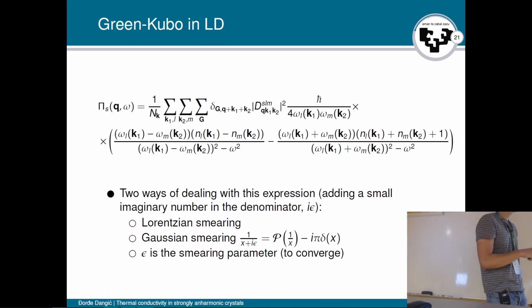Okay, here we have a small technical comment. So how do we actually calculate these things? If you remember, Raffaello was talking that here it's not omega, but actually omega plus some small complex number, plus i epsilon. So we have to add here plus i epsilon. And if we just add this smearing parameter, we don't have to do anything else. We can calculate this expression in that way, and then we get something that is usually referred to in the literature as the Lorentzian smearing, because we have the Lorentzians here.